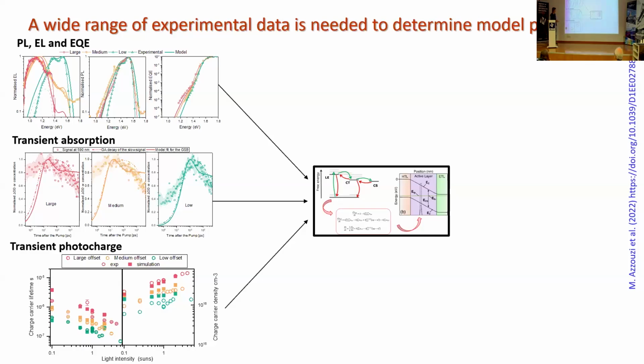There's an example here where for a particular set of materials, we measured not only the current voltage curves, but we measure the light emission from the devices. These are systems with different offsets. And we measure the photo and electroluminescence and the external quantum efficiency photocurrent. We look at the transient absorption kinetics, and we look at the optoelectronic dynamics. And then with that same sort of model, we fit all of those.